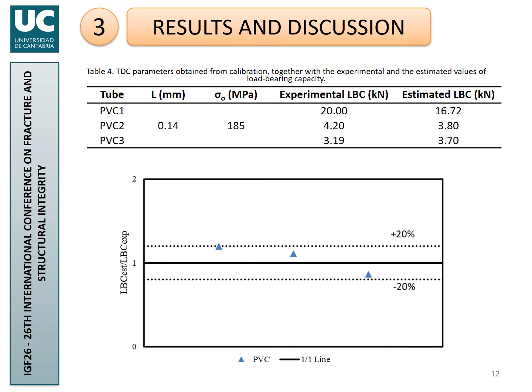If we represent the results in a graph and we assume satisfactory results between plus minus 20% of difference if compared with experimental results, the results are rather good because all of them are between these margins.